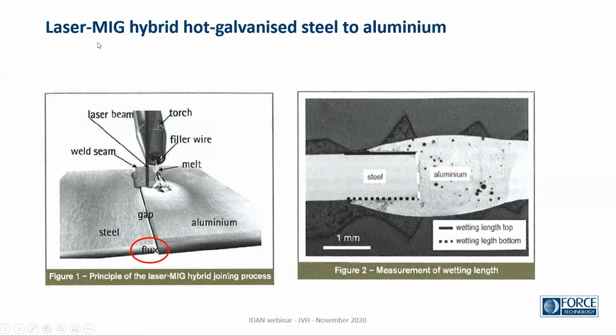An example of laser MIG hybrid welding, where we have a filler material through the MIG torch, and we have a laser as a heat source to melt the filler metal, and that way we could combine aluminium and steel. The result is shown over here, where we have the steel part and the aluminium and the melt between them. As we often see in aluminium, we have some porosities, but the fusion between the two, and the steel is sufficient. These lines indicate what we would measure to control the quality of the weld. How is the wetting length, top and bottom? On the aluminium part, there's no problem, of course.